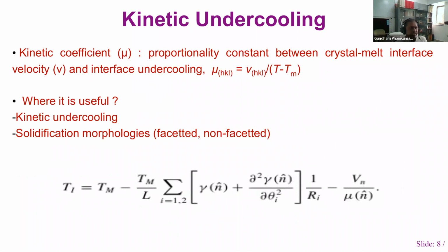Now, the last undercooling is because of the velocity of the interface being very high. That's called the kinetic undercooling. So here is the velocity of the laser or heat source, or velocity of growth, and this is the kinetic coefficient. That's also anisotropic. So a combination of all these terms is what gives you the interface temperature. The interface temperature is not the melting point. It is reduced by a certain magnitude because of the surface tension effects, because of the composition effects, as well as because of the kinetic effects.